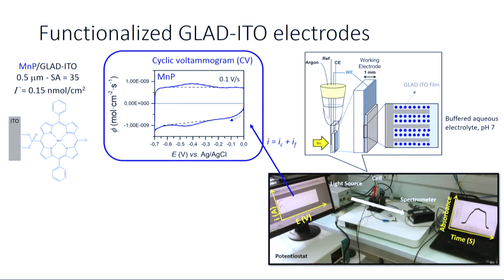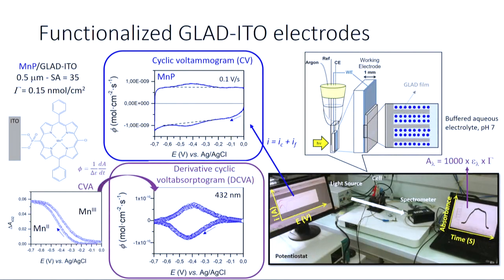So from electrochemistry, here in cyclic voltammetry, we get the typical voltammogram. And what you can immediately notice is that you have a very high capacitive current. And this is the price to pay, because you now have a high surface area conductive electrode. And on top of it, you can see the Faradaic current that corresponds to the redox probe. And now we can have simultaneously an absorbance trace as a function of time, and if you select properly your absorbance, this allows you to monitor directly what's happening at the redox-active chromophore, and here in that case, the reduction of manganese 3 to manganese 2, which is reversible.